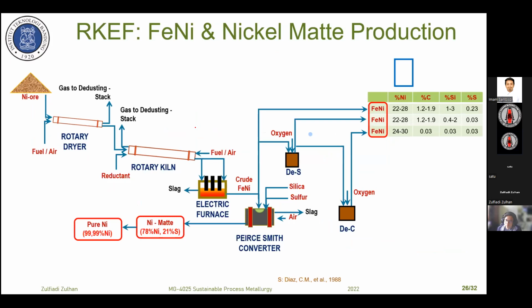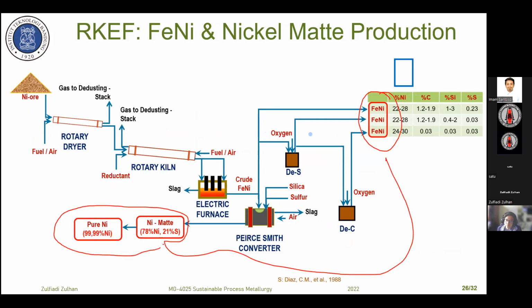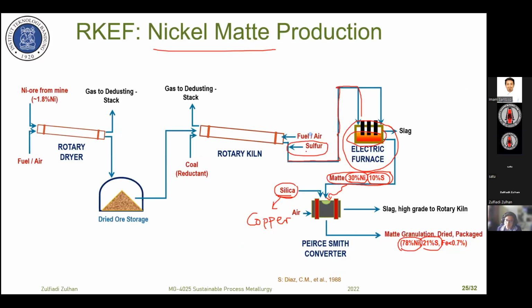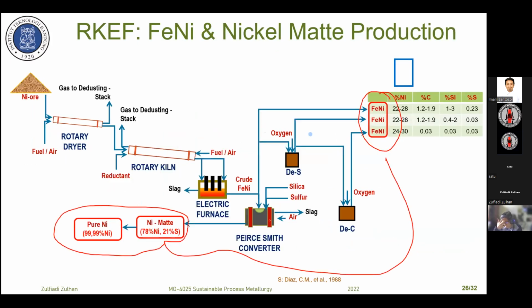And this is the other route in New Caledonia. This belongs to Eramet. They produce both products. They produce ferronickel, and they also produce matte. The difference with this kind of route is that in the previous route, sulfur is added at the end of the rotary kiln. In this route, sulfur is added in the Peirce-Smith converter. Here sulfur is added, and then oxygen or air is blown, and silica is added together. Actually, silica and air are blown in order to remove the iron into the slag.